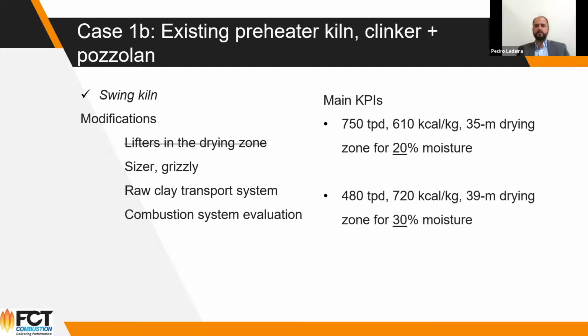And if you want to boost the kiln capacity, you must probably install lifters in the drying zone to cope with probably the same level of production as you had in clinker. So in this case, you're going to have lower capacity, but it's still possible to swing the kiln back to clinker. And sometimes you just have 3, 4, 6 months of kiln idle capacity, and then you can lower the investment and start producing right away with very few modifications. So it's not only disadvantages, but although you're going to be producing less, it's still going to be producing this and back to clinker if necessary.